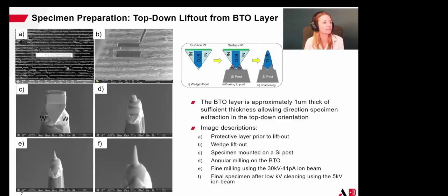Here we've done a standard top-down lift-out process, in which case you will generally be getting several different layers of MLCC electrodes and ceramics. In this case, you may want to adjust your annular milling pattern to target one specific region. In this case, you can see in the mounted wedge in C that we have electrode material on both sides, and we've centered our annular milling pattern such that we're actually sampling the barium titanate region in our mounted wedge, which is the goal of this region of interest. One of the things that you can typically see sometimes with perovskites is a terracing as you're annular milling.